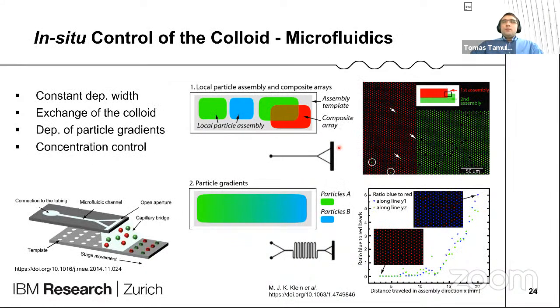The drop tends to dry out, and you lose your nanoparticles. So the idea came from our colleagues again at IBM Research Zurich, that you can apply a microfluidic device to supply this liquid while you're doing the process, because then you cannot only supply a single liquid, but you can have multiple ports, and you can do, let's say, gradients, like shown here. At the beginning, you have red particles, and at the end, you have mostly blue particles, and in between, you have some kind of a gradient.